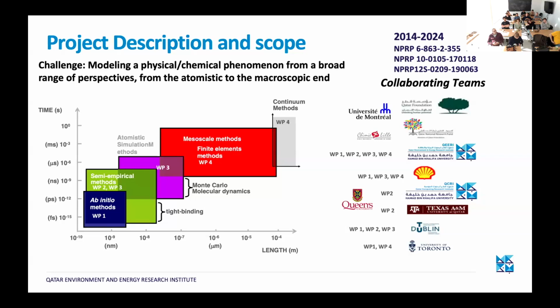You might guess that each of these methods has limits. For example, when we are using ab initio methods, and the first presentation highlighted it very well, we are limited with the system size, and we are also limited with the time that we can simulate, because every force calculation is very, very expensive. Then we go to semi-empirical, where we have seen the case where interatomic potentials can be used or can be fine-tuned, okay? And then you can reach larger systems, a few thousand atoms, and you can reach up to the microsecond. But if you want larger samples and longer time scales, in this case you would need finite element methods to be used.